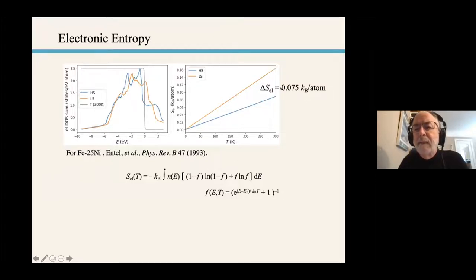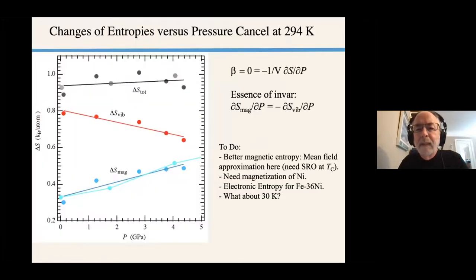But there's a change of electronic entropy that's non-negligible. I'm not sure it's really that big. It's one of the uncertainties today. We haven't finished this work, as I said. But here's what we got so far. Here's the vibrational entropy and how it changes with pressure. It decreases. Here's the magnetic entropy. We've done it a couple of different ways. It increases with pressure as we disorder the spins.